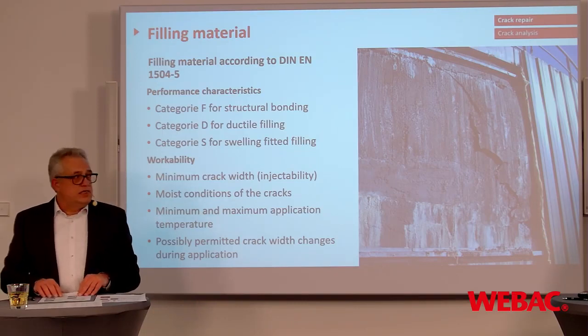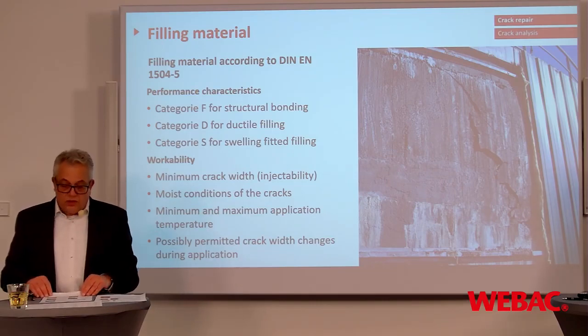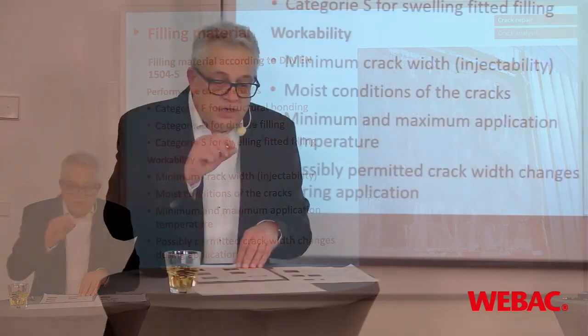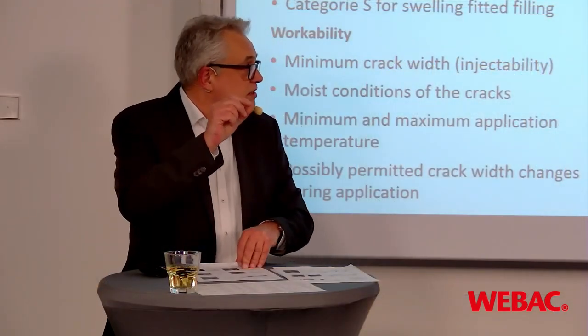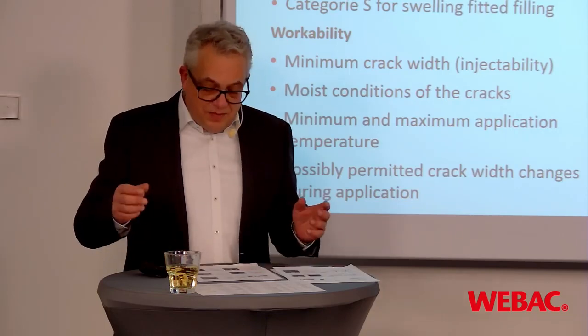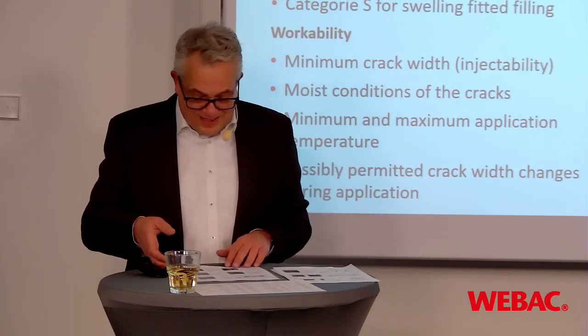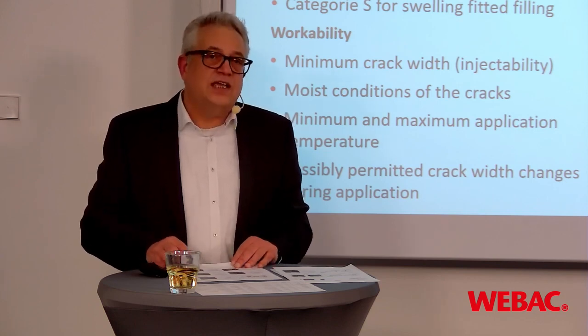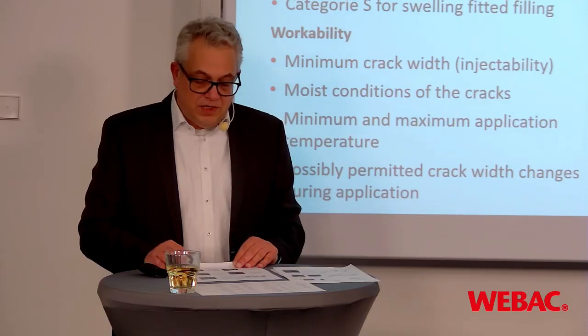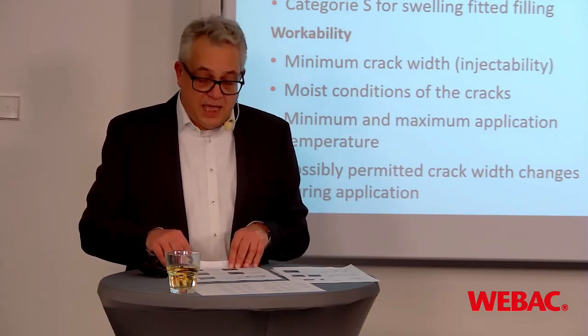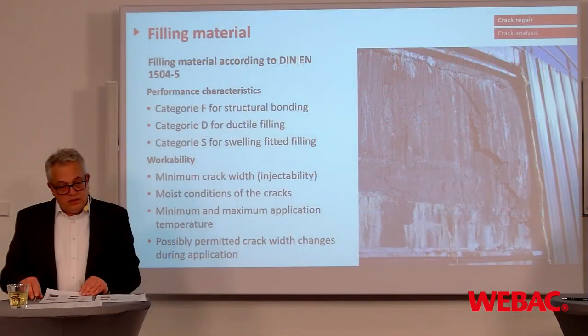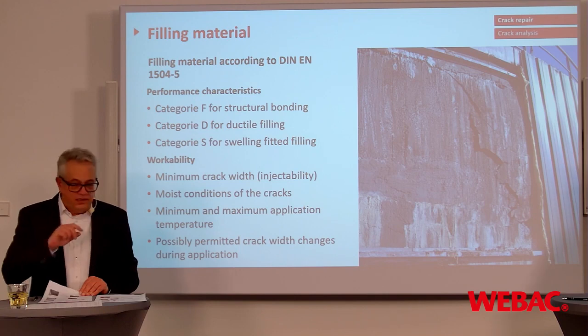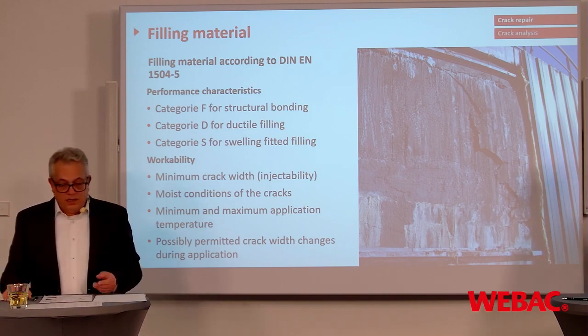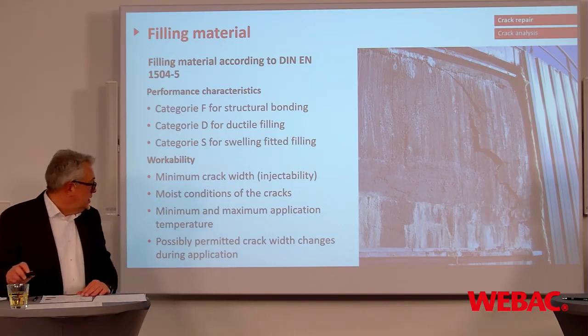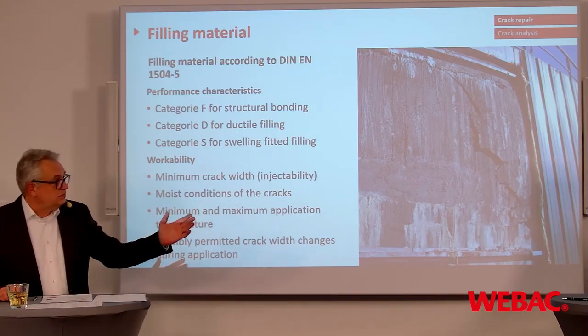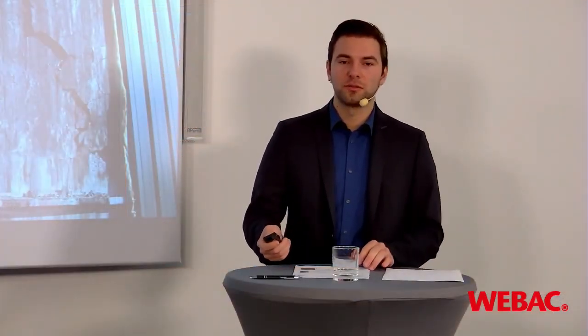On the workability side, as you already mentioned, it is important to know the crack width. You cannot inject a crack of 0.001 millimeter. That's simply not possible, but it will be dry anyway, so there's no need to. You have to take into consideration the minimum and maximum temperature, and also the crack width change during the injection. Okay, Maurice, now it's your turn with a comparison of impregnation and injection.